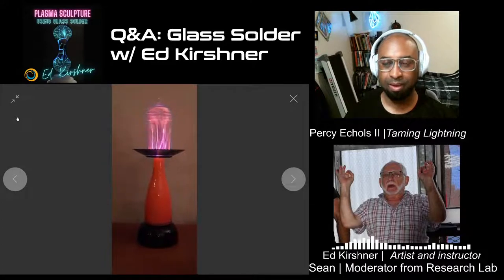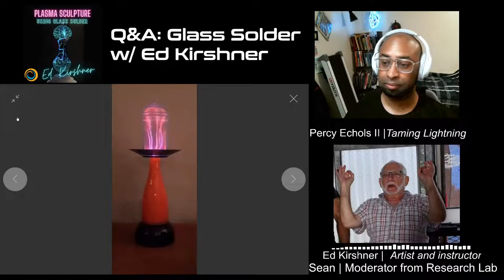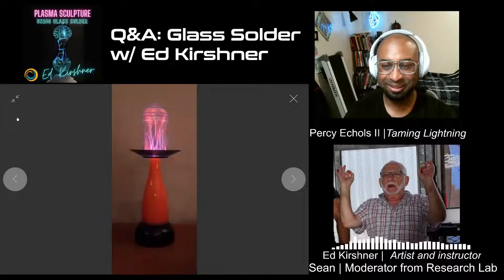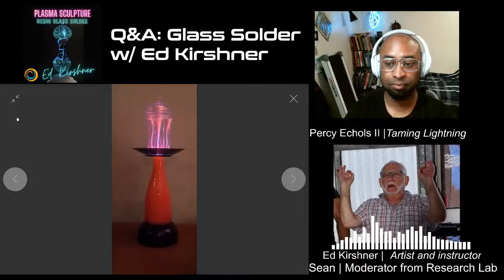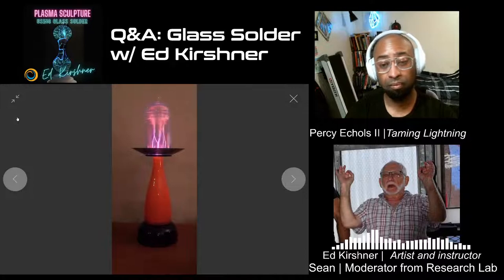And now the neon electrode to crystal is very easy. I mean, they match. It's a lead glass. You just have to be careful that you can't go up quite as high with the solder. There's a trade-off there. This one can slump, and at a certain point, the solder is not going to flow. So to compensate for that, as an aside, I developed a separate solder that melts at 800 instead of 925.